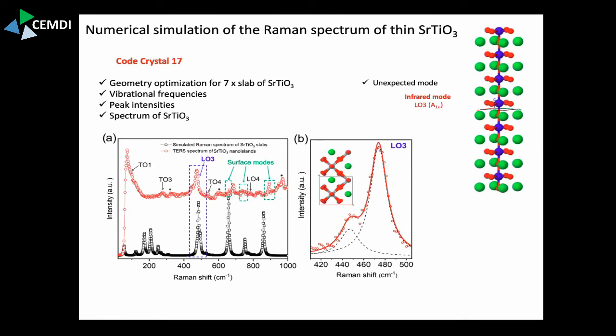So we were calculating this because it was a thin film, or we consider it a thin structure, with 7 slabs. So this was 7 unit cells. We made it an uneven number to have something in the middle and not be just 3-3 symmetric. And so we optimized the geometry in the first place, then calculated the vibrational frequencies, then the peak intensities, which is the del alpha del Q squared. And then there is some symmetry related degeneration. So several peaks occur multiple times because they're symmetry related. So this multiplicity is also considered automatically. And what came out is that this mode here, the most intense one, is actually an infrared mode. It shouldn't be there.